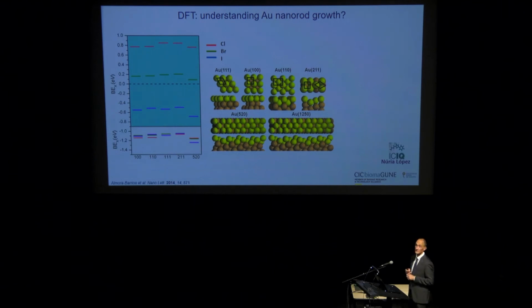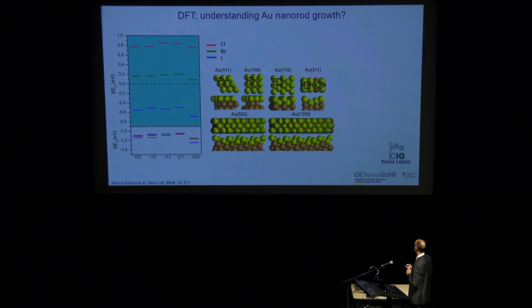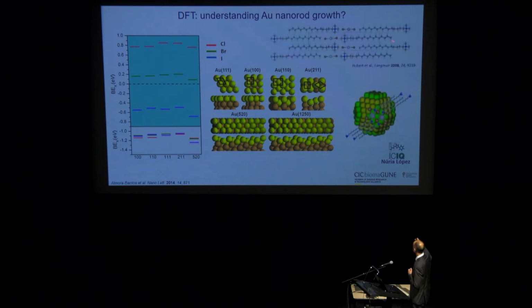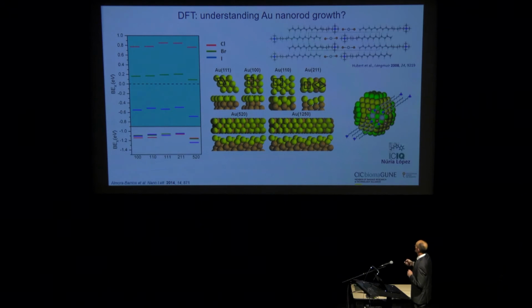Another piece of evidence behind the attachment of the surfactant on surfaces comes from theoretical analysis, density functional theory calculations by Nuria López at the ICIQ in Tarragona. And for this analysis, we actually also used the presence of these complexes between silver ions and CTAB, which were also proposed by Olivier and his student Fabien Hubert. And by doing that, you can understand that the stabilization of the 520 facets at the sides makes sense from a theoretical point of view. From a thermodynamic point of view, I have to acknowledge that kinetics is not yet involved in these calculations and should also come into play.